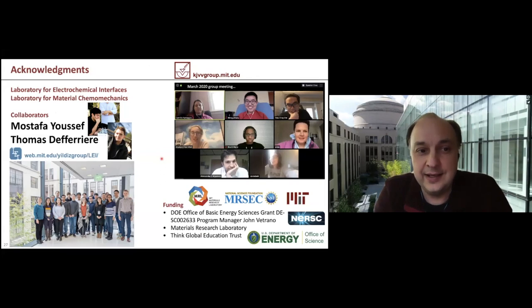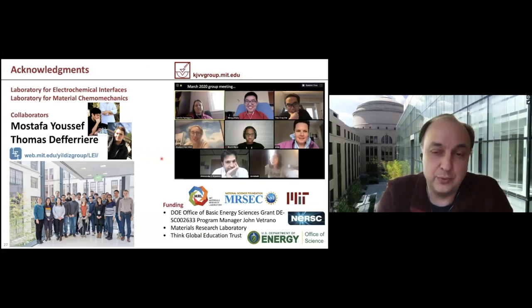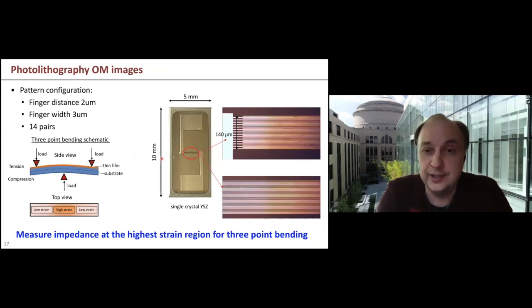So the tests of the strain on your metal oxides are very much dependent on the design of your substrate. You pointed out that the center part of your substrate is a point where there is zero tension or compression, and then above or below there is tension or compression. Clearly, with the change in temperature, which is what you're modeling, the substrate itself will also have different types of mechanical responses to that temperature change. So how do you account for that, or the interface between the substrate and the metal oxide will similarly have additional, call it confusing elements in being able to identify the true nature of the oxide itself?